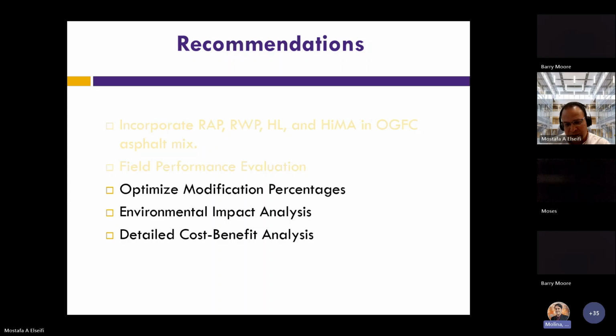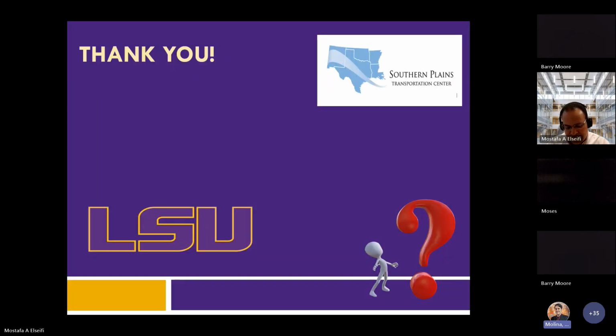Right. We have one last question. In Oklahoma versus the wet climate of Louisiana, would it be better to study fly ash instead of hydrated lime as an additive? So that's a good point. I think fly ash, the concrete industry is using a significant portion of it. So I think there is a type C and type F, and I think type F is a good one. And sometimes when we try to use fly ash in our research, we have problems finding it because it seems the concrete industry is using most of it.